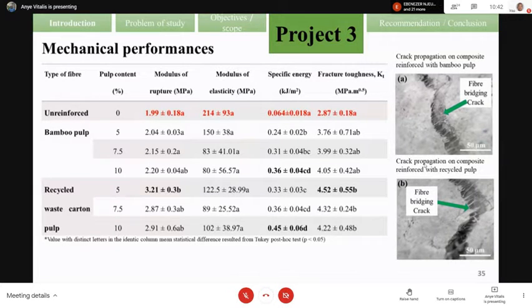We realize that by introducing the fiber in the bio-based material, they are increasing the modulus of rupture, increasing the specific energy fracture toughness, but they are reducing the elastic modulus. We're showing that by introducing fiber, our material, which was a purely brittle material, can transit from brittle to ductile material. The fibers significantly improved the crack propagation resistance of our material, which can be shown in the fracture toughness. Also, by studying the crack tip, we realized that a crack bridging mechanism was present in the crack tip region.